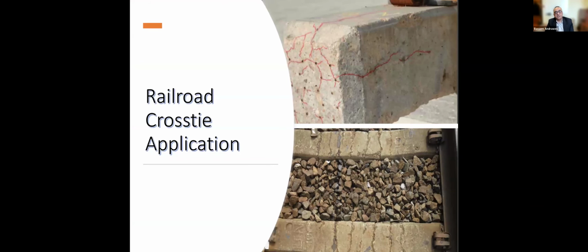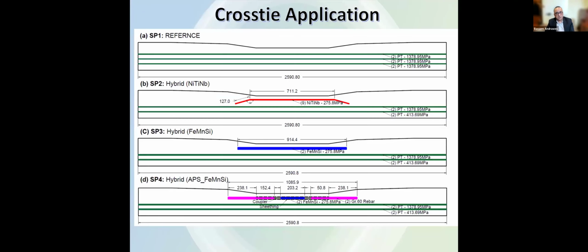Let us switch to another transportation mode now, leave highway and move to railroads. They have their own set of issues and problems, especially when it comes to precast, pre-stressed concrete ties, like the ones I'm showing here, like end splitting crack problems, like center region cracking problems. So we started having discussions with experts in this area. Especially we started working with Rocla Concrete Tie, one of the leaders in developing these ties in North America. And we told them, how about if you eliminate the top layer of your post-tensioning wires? That will help, of course, alleviate some of the stress at the end zones, which will help with the end splitting crack issue that they have.